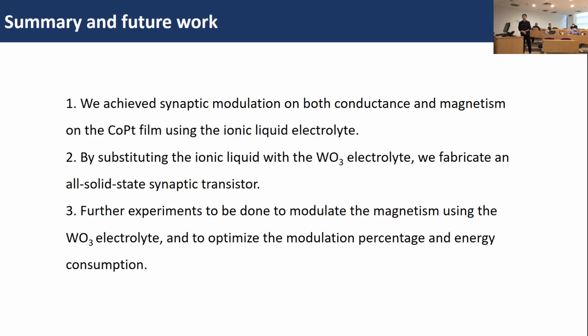Okay, to summarize, here we achieve a synaptic modulation on both conductance and magnetism using the ionic liquid as the electrolyte. And we also achieve a similar effect by changing the ionic liquid to the tungsten oxide as electrolyte. For the future work, we are going to use the tungsten oxide electrolyte to optimize our modulation percentage and the energy consumption.